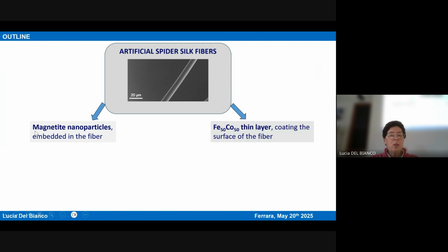And we tried two different strategies. So the first one was to embed magnetite nanoparticles into the fiber. And the other strategy was to coat the surface of the fiber with a thin layer of iron cobalt, which is a ferromagnetic alloy, a nanometric thick layer.